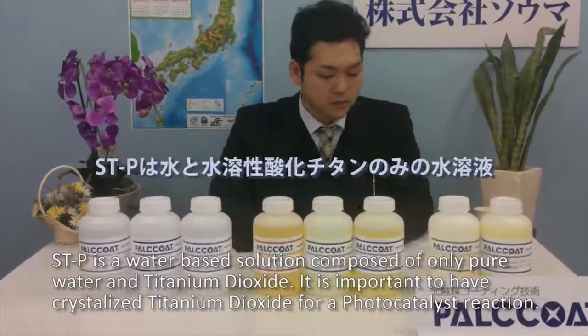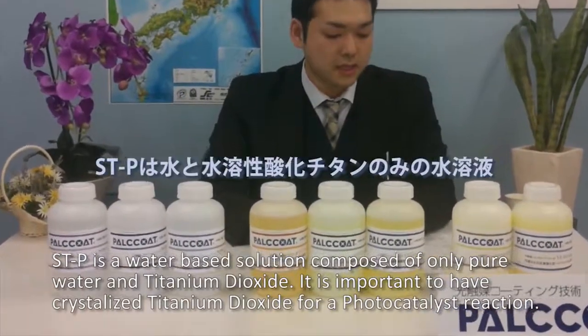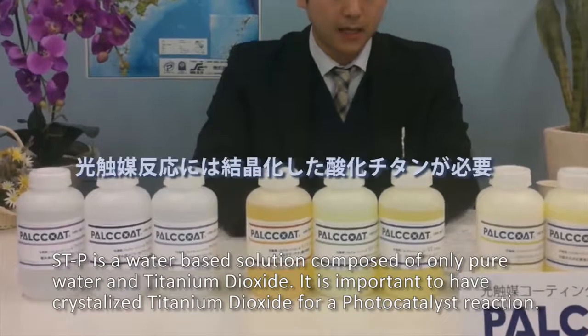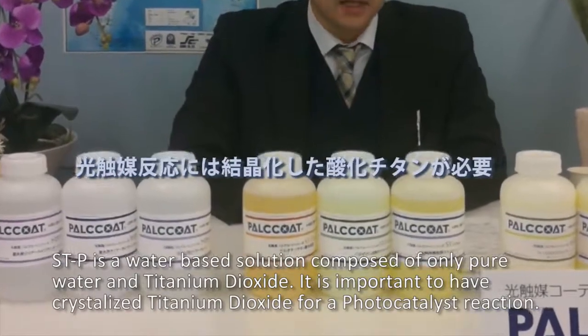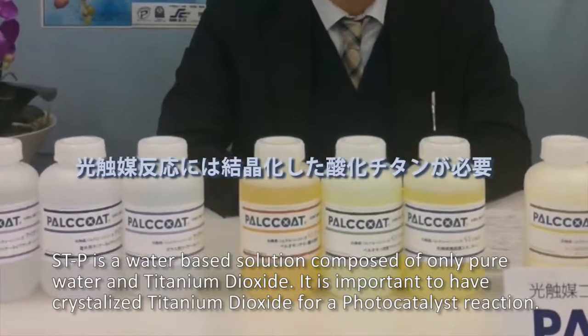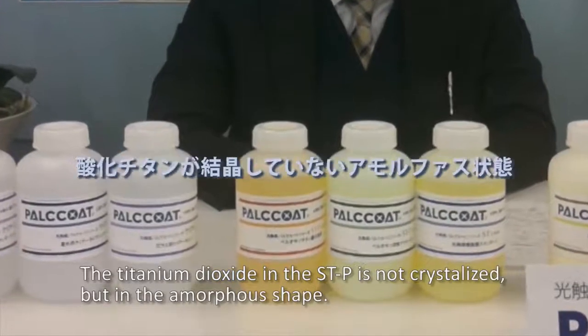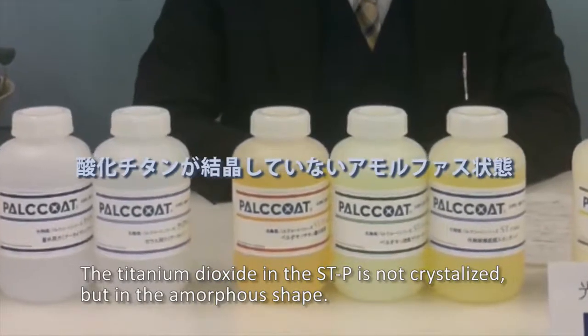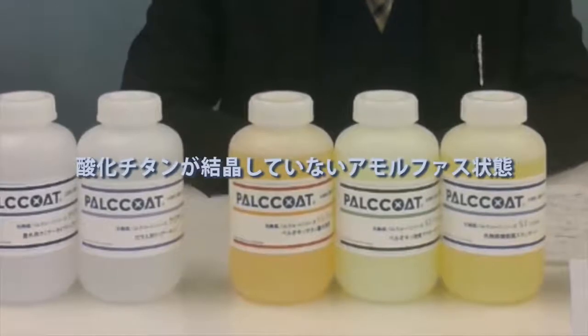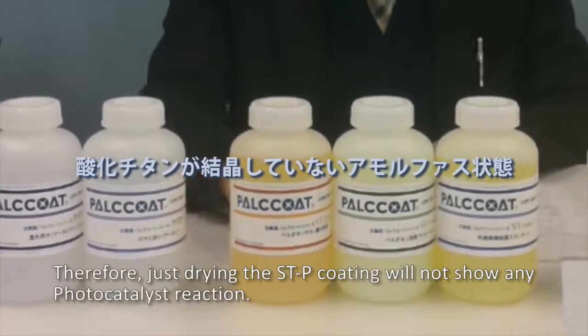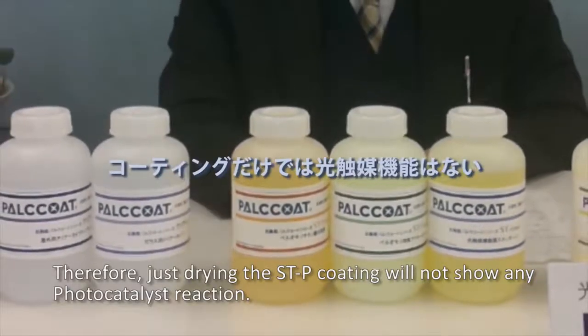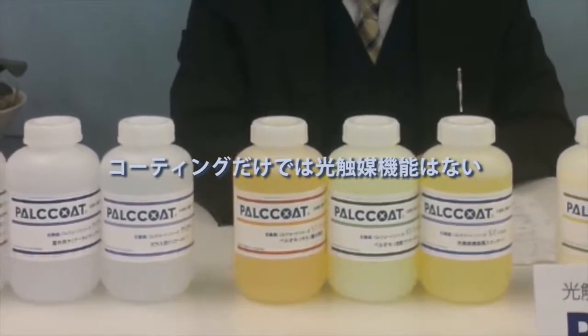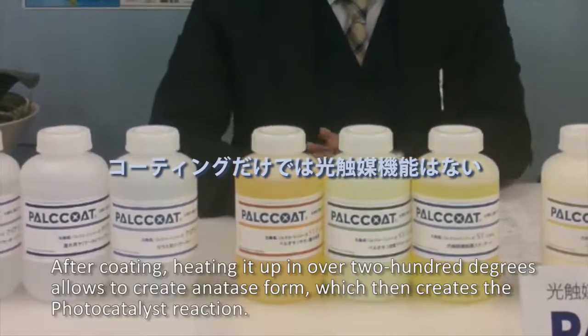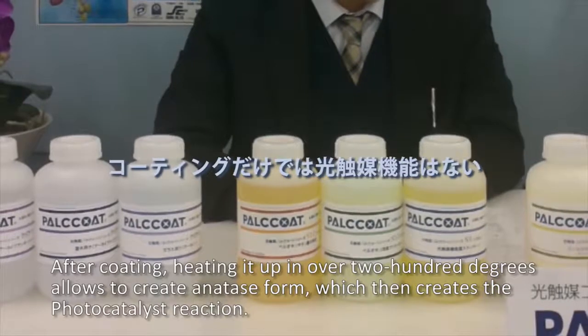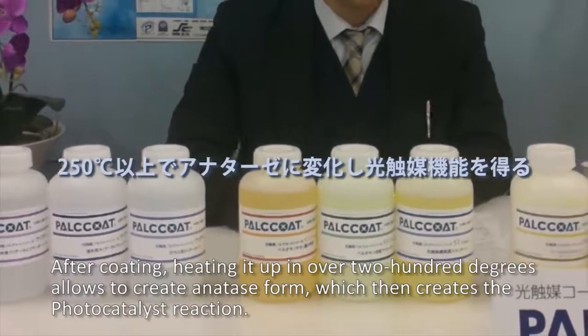STP is a water-based solution composed of only pure water and titanium dioxide. It is important to have crystallized titanium dioxide for a photocatalyst reaction. The titanium dioxide in the STP is not crystallized, but in amorphous shapes. Therefore, just drying the STP coating will not show any photocatalyst reaction. After coating, heating it up over 200 degrees allows it to create the anatase form, which then creates a photocatalyst reaction.